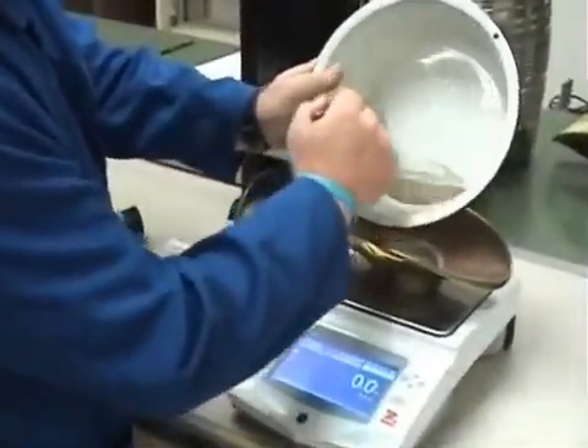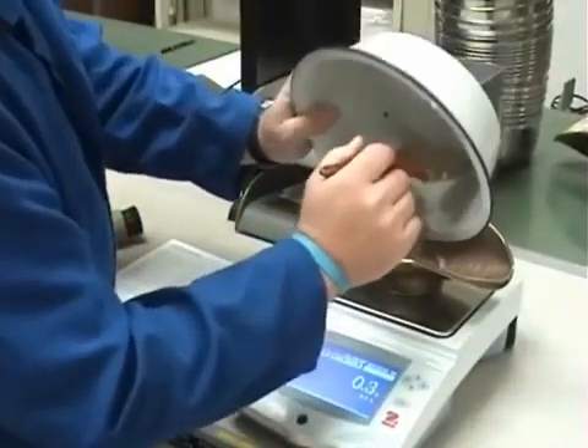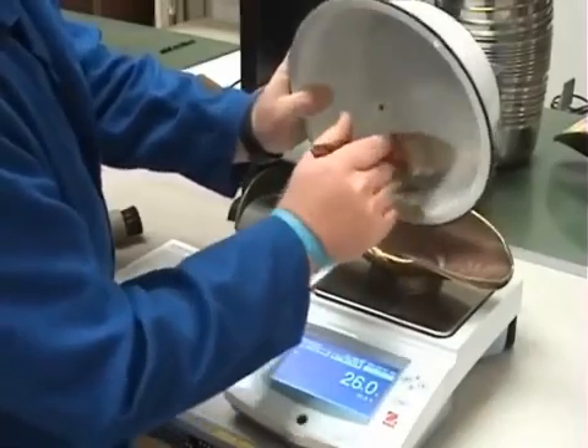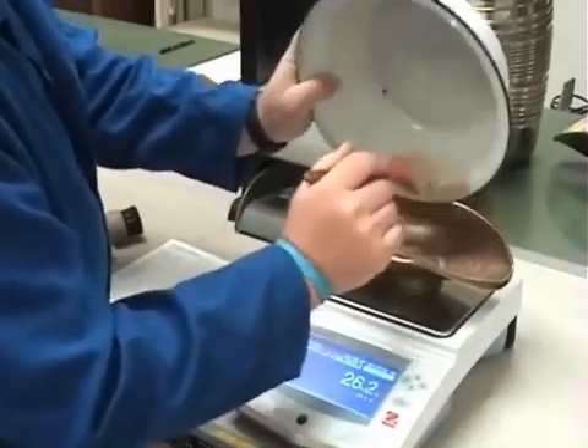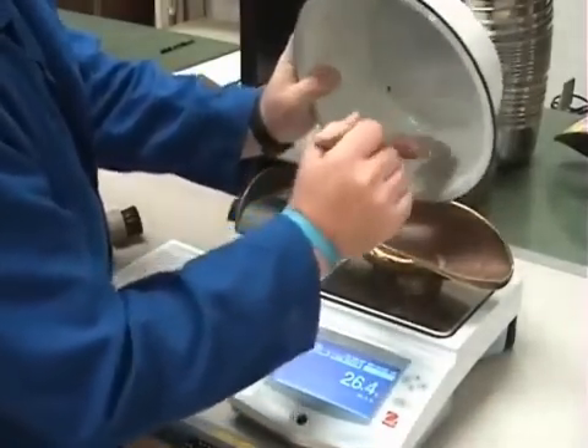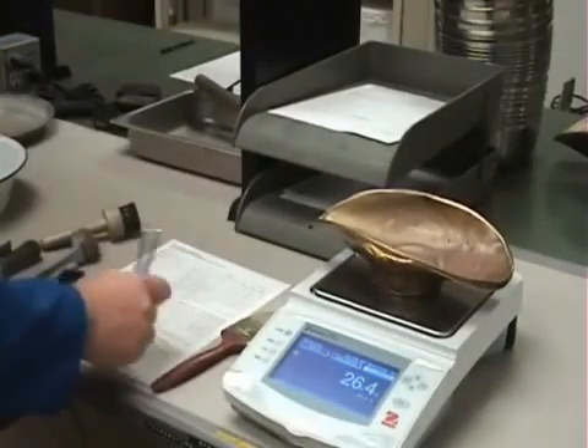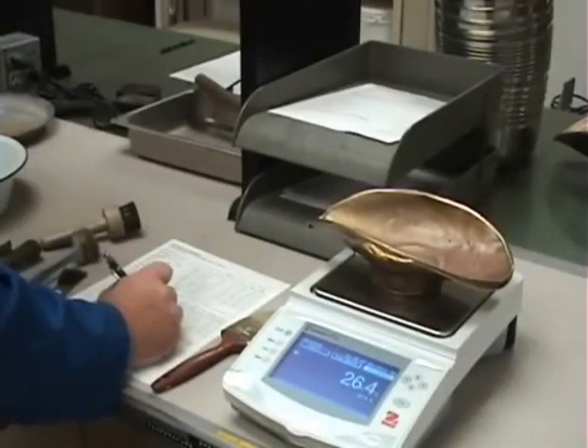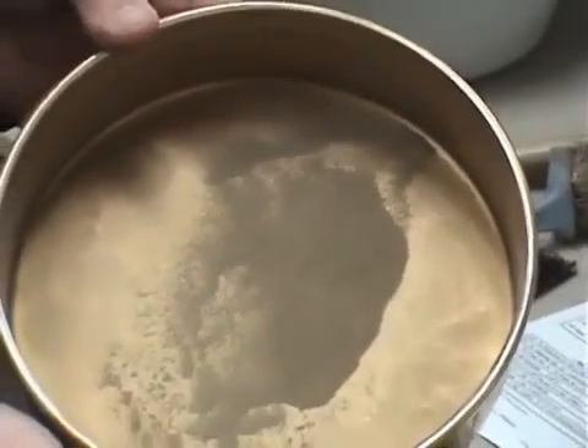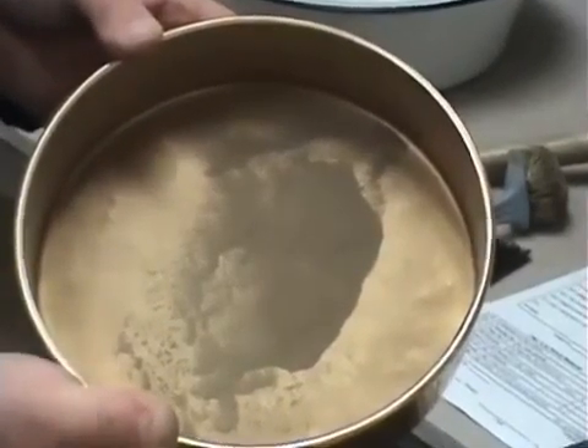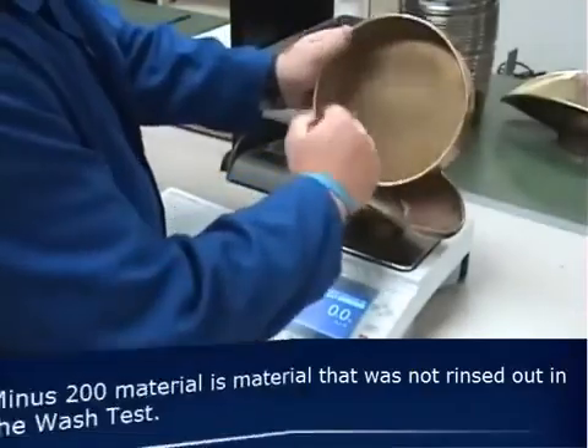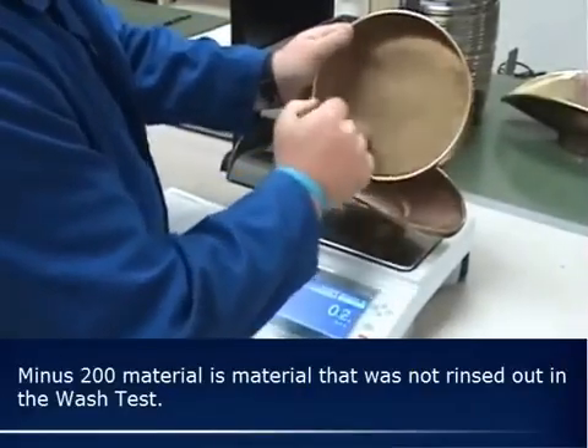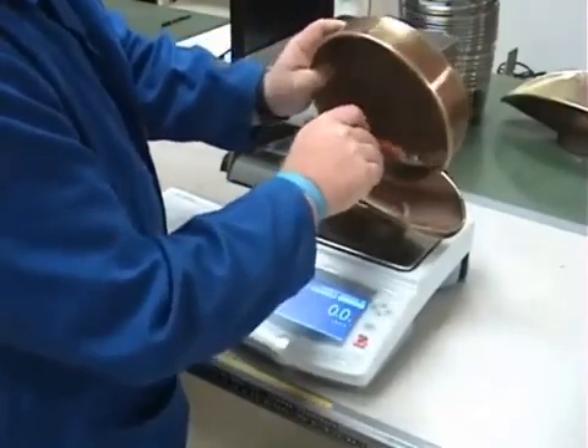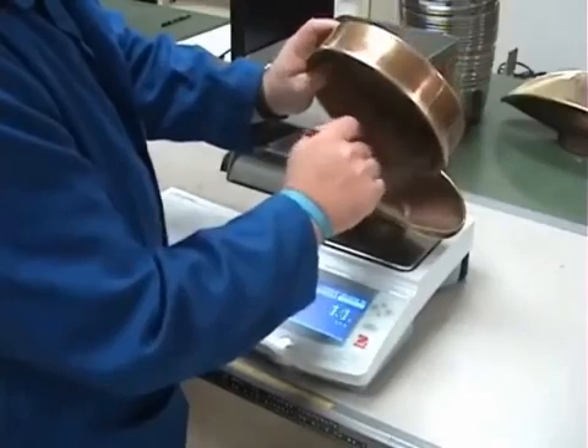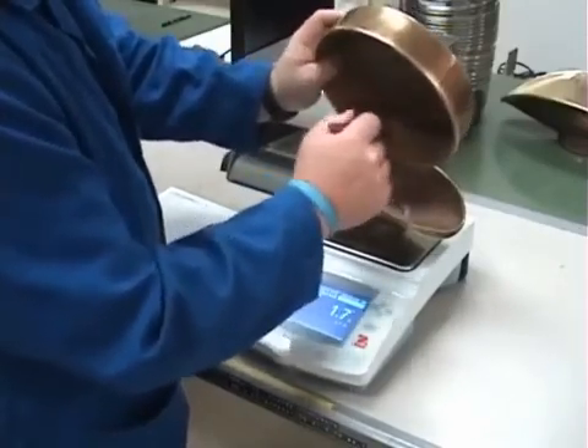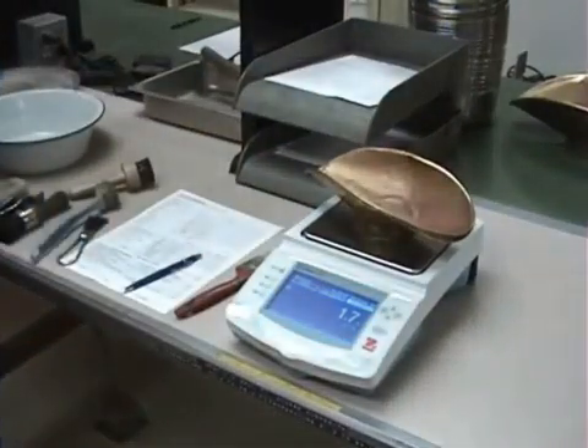Weigh and record the material retained on the number 200 sieve. Be careful to not lose any material. The material in the bottom of the nest of sieves is minus 200 material. This material is weighed and recorded. The minus 200 percentage is derived from both the wash and sieve analysis tests. Weigh and record this weight. In this case, it's 1.7 grams.